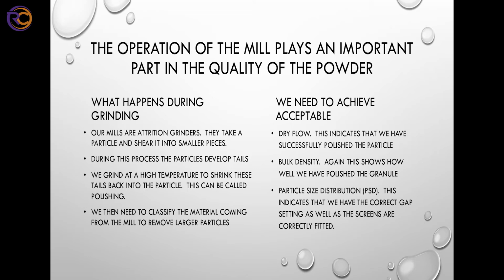During the grinding process, the particles actually develop some tails. And we actually grind at really high temperatures, as I said before, very close to the melting temperature, so that we can actually polish the particles and take those tails off. So we need to actually classify the material coming from the mill to remove all the larger particles, which, as I said, gets reground.